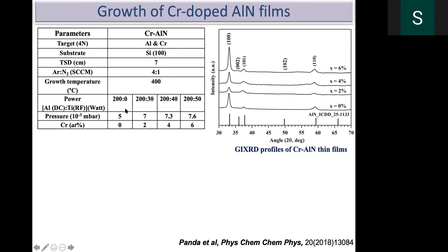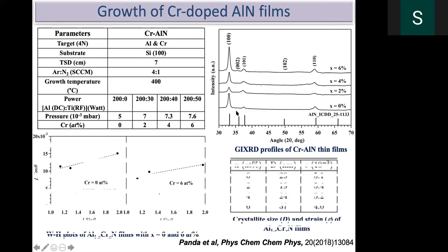I don't want to go deep into what kind of power we changed, but the pressure was changing because of this change in power, but always in the 10 power minus 3 millibar range. And the peak position did not change much, but the intensity increases. That means grain growth is more.